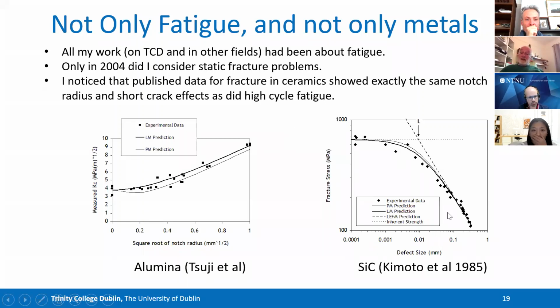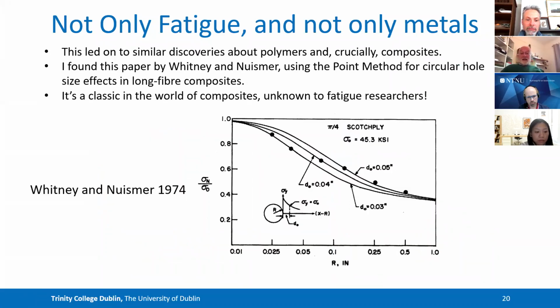So this could be a Kitagawa diagram plotting the fatigue limit against crack length, except it happens to be a diagram plotting the fracture stress of ceramics against defect size, but it's got exactly the same kind of curvature. Likewise, the notch data comes out the same. And so the critical distance theories like the line method and the point method worked perfectly with this problem as well. So that was exciting for me to realize that.